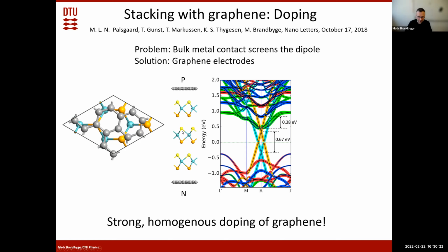So if we take this stack of three Janus layers and sandwich it between graphene electrodes, then we would have a strongly n-doped graphene electrode on one side and strongly p-doped on the other side. So we would have a quite nice diode structure from the built-in dipoles. You see in the band structure how this crossing here is actually the band structure of the graphene, and you can see how it's strongly n-doped on one side and strongly p-doped on the other side. Okay, so this is kind of interesting.